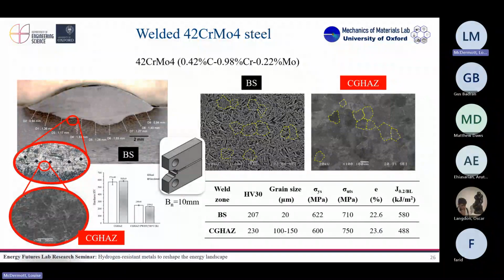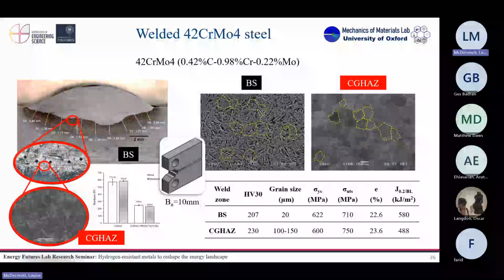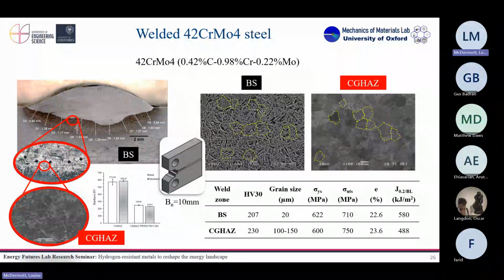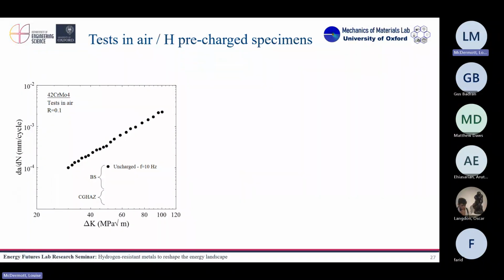Because the welds are usually the most sensitive area of a structure. It's where we join different parts, and it's usually where we have more defects, where we have more interfaces, and where the material is inherently more brittle. So we have more defects, and hydrogen loves defects. So what we did was to do fatigue crack growth tests.